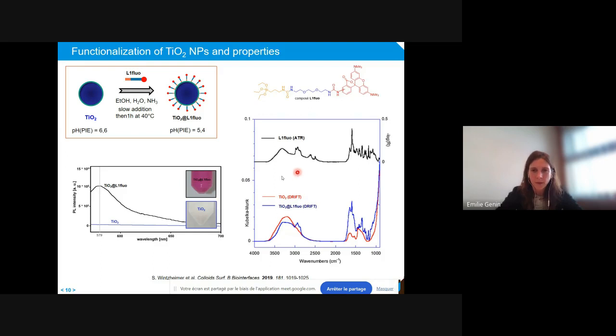Infrared experiments were also very valuable for us because here you can see the spectrum of the organic ligand, and in red you have the pristine nanoparticles. In blue, that's the infrared of the hybrid system, and as you can see, all characteristic bands of the organic ligand are clearly visible, proving the functionalization.